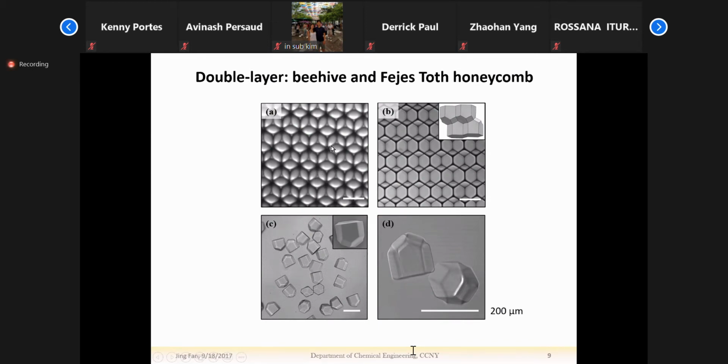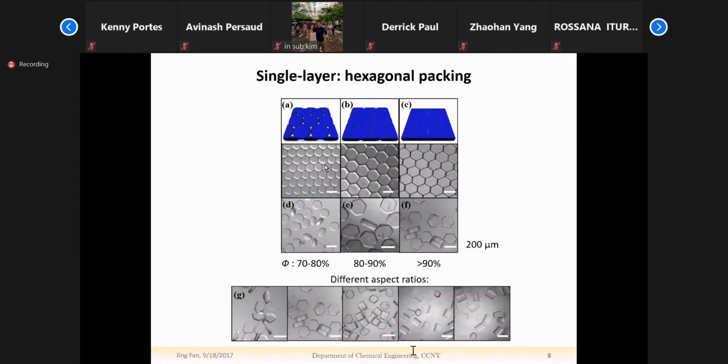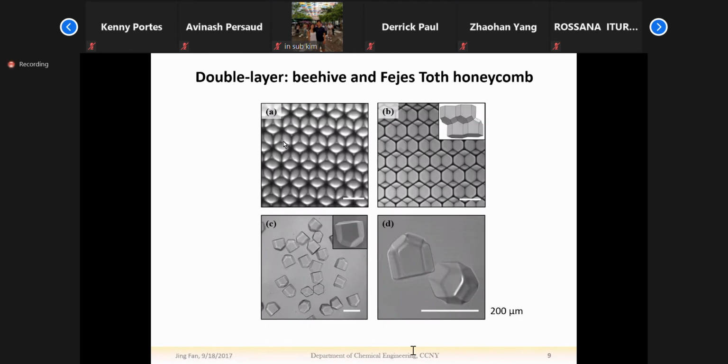You have 2 layered droplets. Each layer is in a hexagonal packing. Hexagonal packing means this one. This is the densest packing that you can get for monodispersed spheres. So you have 2 layers of this hexagonal packing. And also, to reach the highest packing density, each droplet will sit in the middle of 3 droplets from the other layer, right? So that's why you see this structure. For example, this droplet sits in the middle of these 3 droplets.